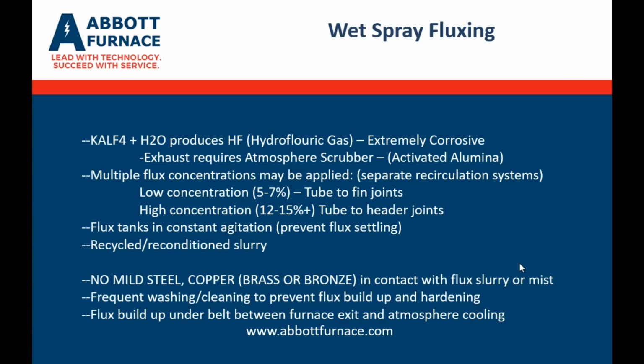That mist adheres to the outsides of the furnaces, to other equipment around the furnaces, to the building, the support columns in the building, things like that. So frequent washing and cleaning is very important when you're using your wet flux because it does build up and get very hard. So part of the design of the fluxer is incorporated to prevent flux buildup and to aid in easy cleaning.